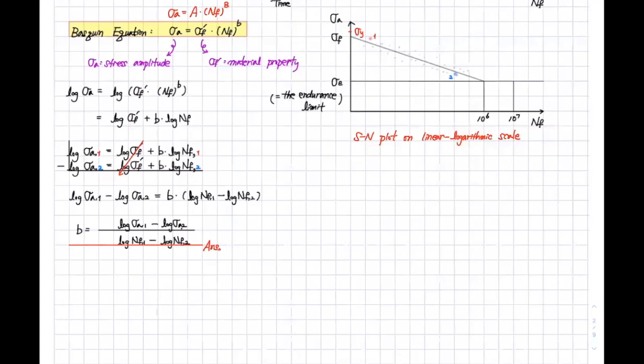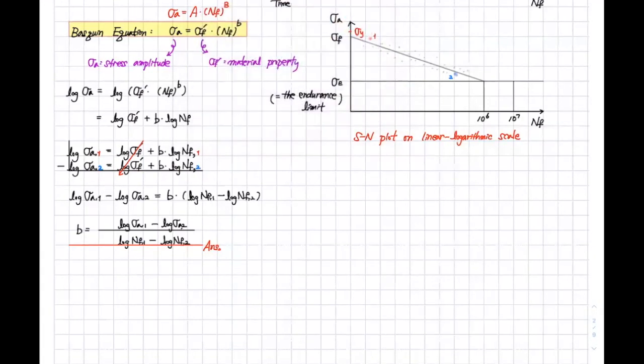Before going further, I have very many problems after this, but let me mention something. This endurance limit is kind of a reference, a minimum stress amplitude which will not break in cyclic loadings, and it could be affected by numerous sample preparation conditions or post-treatment of the materials. So it's very important for you to understand how we can increase or decrease it by different setups or conditions.